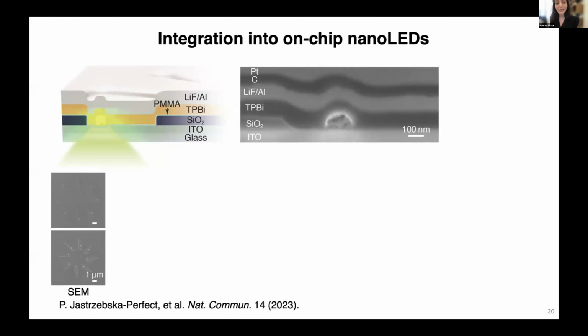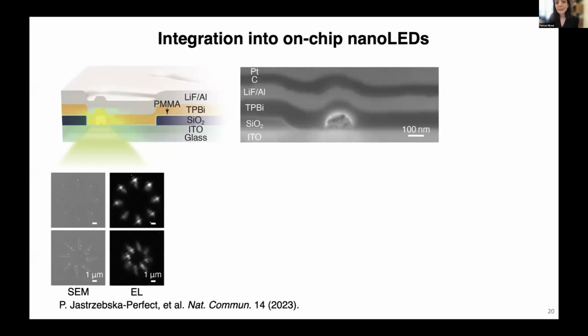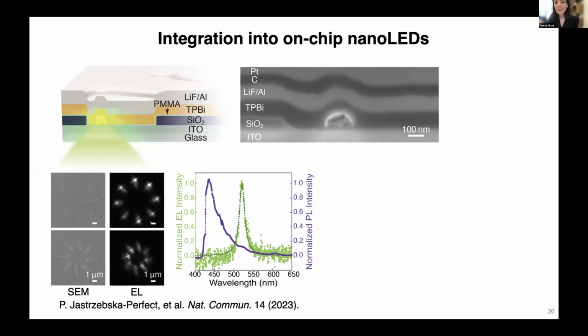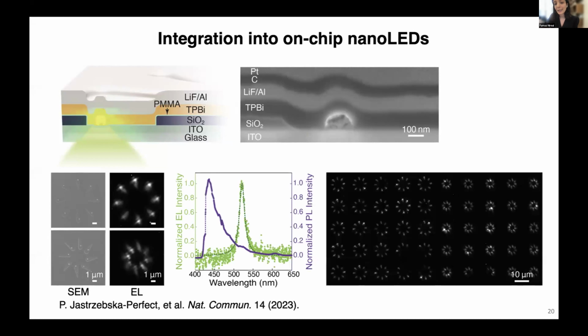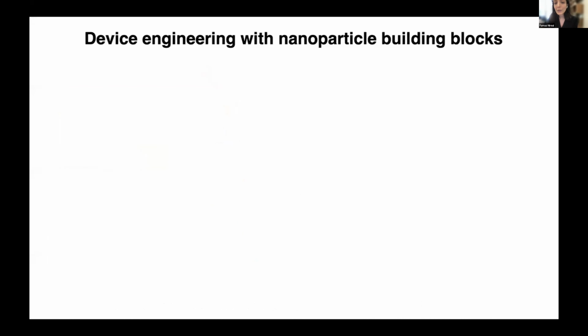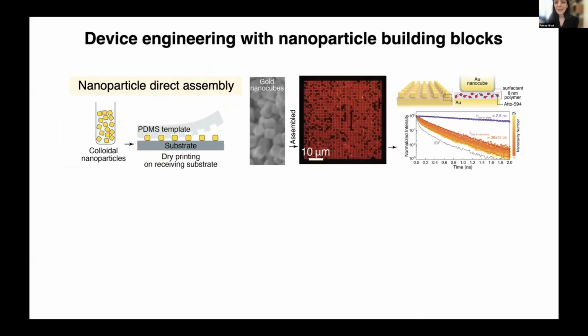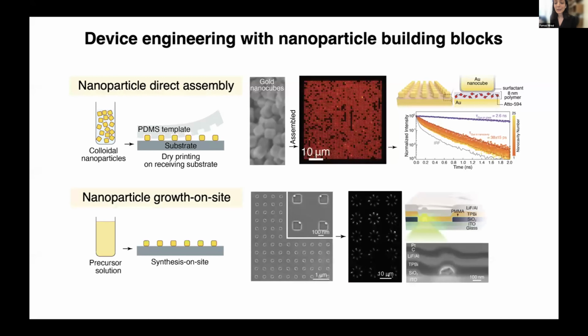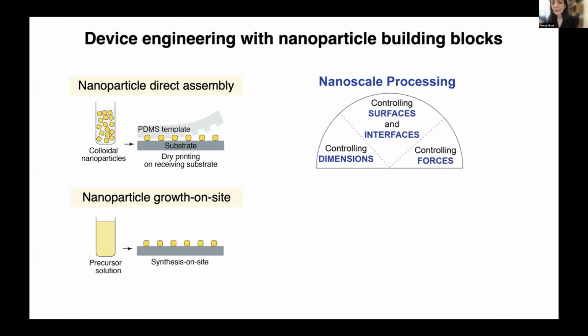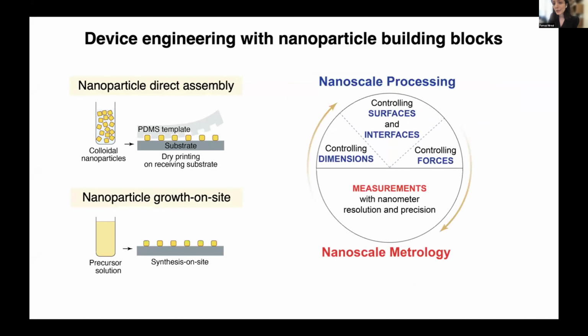I'll end with the last two slides, where our approach now allows us to take these individual nanocrystals and incorporate them into more complex devices. Here, showing you the first demonstration of deterministically formed nano LEDs out of individual crystals of halide perovskites, in particular cesium lead bromide, opening up many opportunities for use of these high density on-chip integrated LEDs. So just to end, I hope I was able to give you an idea of the prospects of being able to achieve nanoscale control over individual nanoparticles for their integration into emerging nanoscale devices. Along the way, of course, there are going to be processing challenges that have to be addressed, as well as metrology challenges.